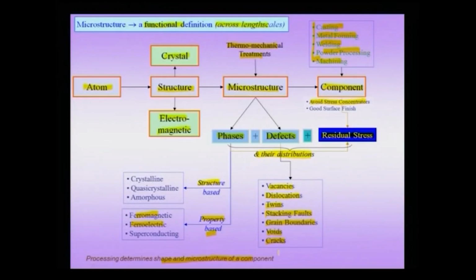Therefore, this is perhaps one of the important slides in this whole lecture or this whole course, because now we have not said anything about the scale of the microstructure. We have not said that it is only at the micron scale. For instance, in the case of the GP zones which we talked about, which are essentially copper rich regions in an aluminum copper alloy matrix, they would have a length scale of the order of nanometers. Not only that, these GP zones are coherent in nature, that means GP zones have a residual stress field associated with it. So, this is an important concept now that we have GP zones.